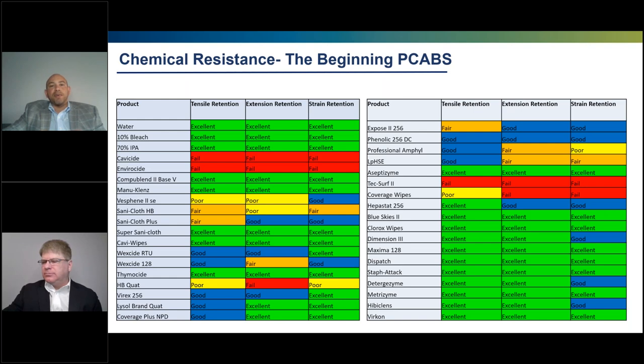The alloys are great because they balance each other. PC is gonna give good flammability and impact values, which ABS lacks. And then the ABS comes in to increase the overall chemical resistance that polycarbonate lacks. And you can see here about 40 to 50 different cleaning agents and chemicals that are out there, where we did that chemical testing and we give it a grading system.